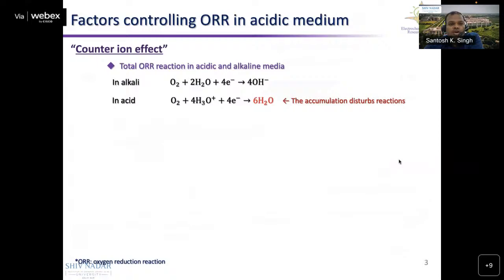If you talk about the counter ion effect, we know that if you see the fuel cell reaction in the alkaline anion exchange membrane fuel cell and in the proton exchange membrane fuel cell. In alkali medium, oxygen gets reduced at the cathode, and the OH minus travels through the anion exchange membrane to the anodic side, and the water is produced at the anode side. So there is no problem of water accumulation at the catalyst side in the anion exchange membrane fuel cell, which does not block the active sites.